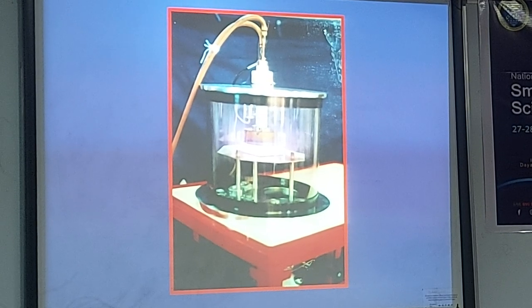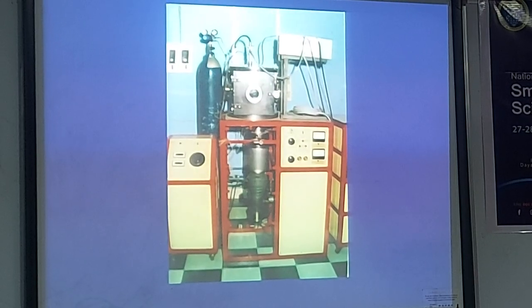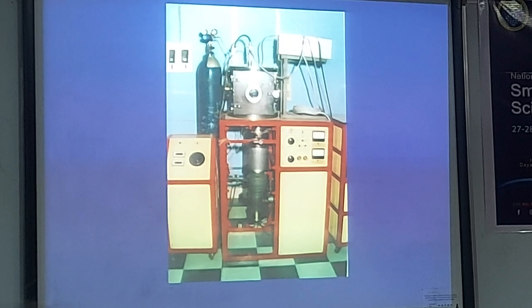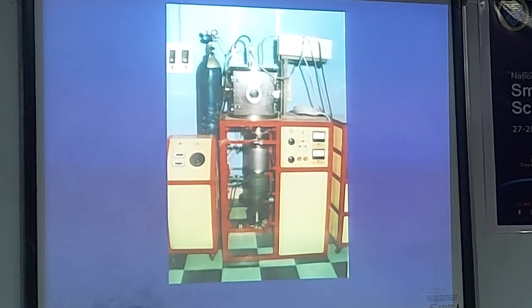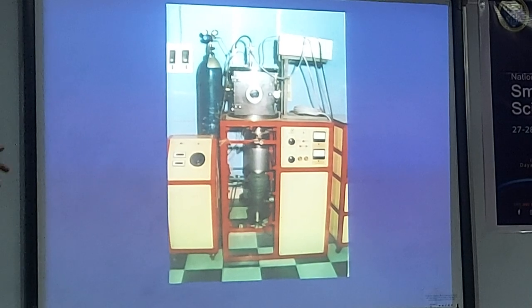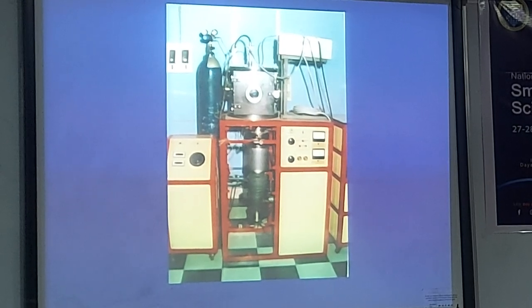So just to give an idea how the plasma looks like, I have taken this slide. This is a metal chamber, a box type metal chamber. This was also made in our laboratory by our student. On the lower side, what is shown is a diffusion pump, backed by a rotary pump. This is the RF power supply. This is a gas cylinder. Normally, the inert gas argon is used. Sometimes, in order to do reactive sputtering, in addition to argon, we also use a reactive gas like oxygen. Then it's called reactive sputtering. There are various versions of that.